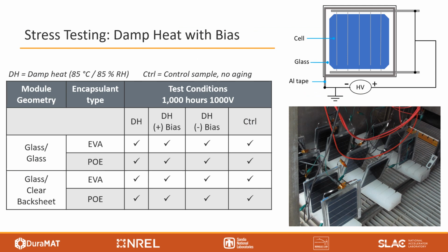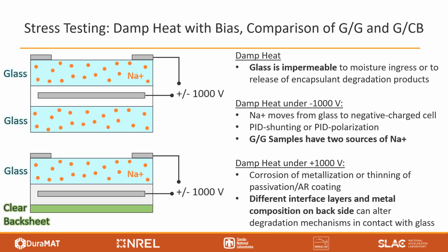So the samples for accelerated stress testing consisted of glass-glass and glass-clear backsheet modules, each with either an EVA or a POE encapsulant. Here I'm showing a photo of the samples in damp heat under the different bias conditions, where the bias is applied between the cell and the module frame, and the frame is simulated by an edge of aluminum tape. Under accelerated stress, there are a few different possible impacts of the module construction on the degradation mechanism.